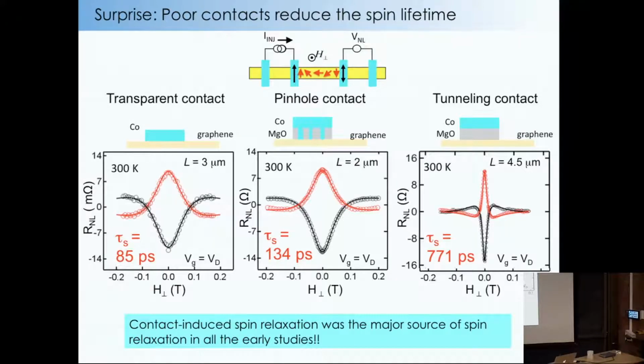What we realized was, in fact, the worst thing in the device was the contact. If you have a contact that's really interacting with the graphene, the tendency is for it to start killing the spins one way or another. But if you make a good tunnel barrier to isolate the ferromagnet, then you can have a much larger spin lifetime. This was a big advance because there was a big mystery: why is it so short? At least we solved the first step, which is the contacts.